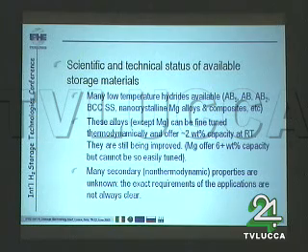The status that came out of the meeting is that there are many low-temperature hydrides available: the intermetallic compounds AB5, AB, AB2, the body-centered cubic solid solution, nanocrystalline magnesium and alloys and composites. These alloys, except for magnesium, can easily be fine-tuned thermodynamically, but offer only about 2 weight percent. The general feeling is that 2 weight percent will certainly fit in many smaller scale applications, depending on the price of that 2 weight percent.